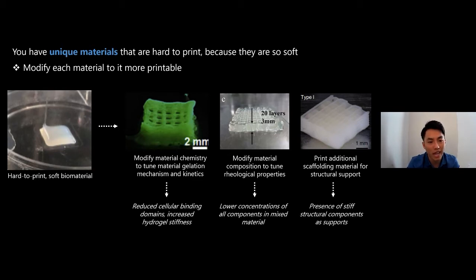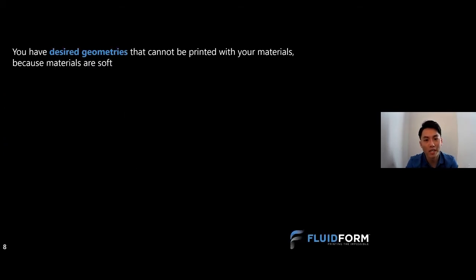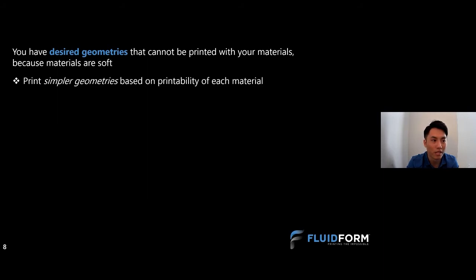And then when you're printing these scaffolding materials, you really need to then think about how do I deal with the presence of these very stiff structural components that I don't really want in my construct, but they are necessary as supports, right? And then so, because we need to so finely tune each material so that they become printable, we usually don't have quite the perfect printable material. We usually add an in-between point where materials are somewhat printable, but they need to be printed in simpler geometries that are designed around the challenges of printing them, right? So, this is our second problem.